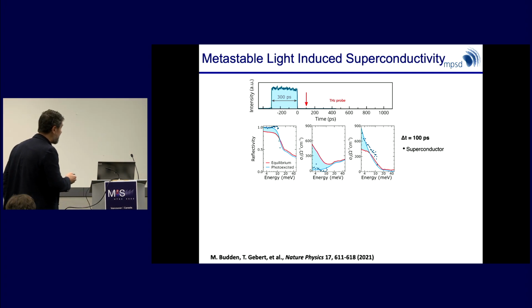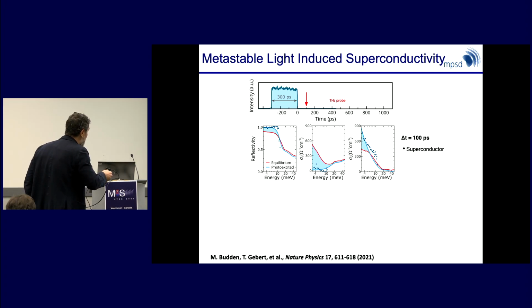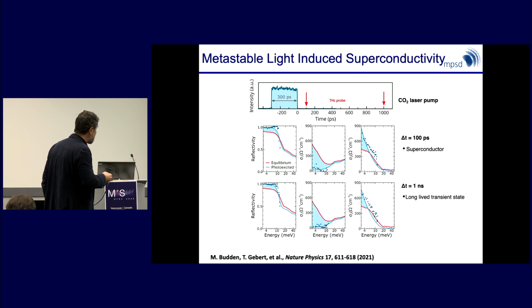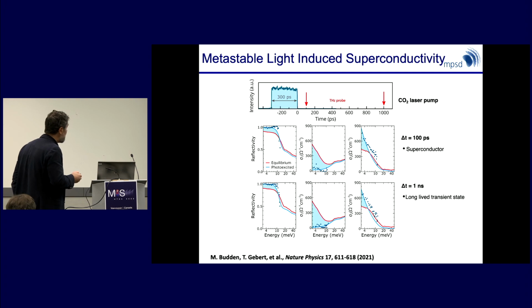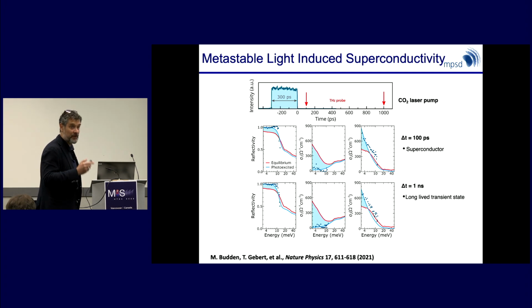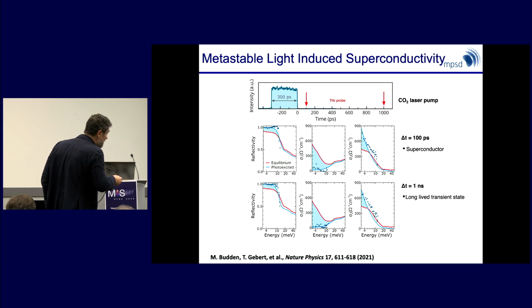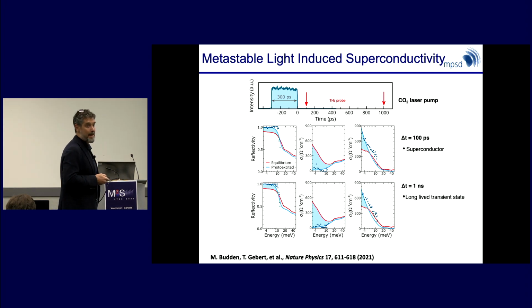But what you can see is that whilst in the previous experiments, the effect would be confined to 1 picosecond immediately after the pump pulse, if you look, this is my pump pulse of 300 picoseconds. If you look at the transient sigma 1 and sigma 2 and reconstructed reflectivity at various time delays after this excitation with a long pump pulse, we observe a metastable state that lives for about 1 nanosecond, which has, again, extremely suggestive features of superconducting-like optical properties.